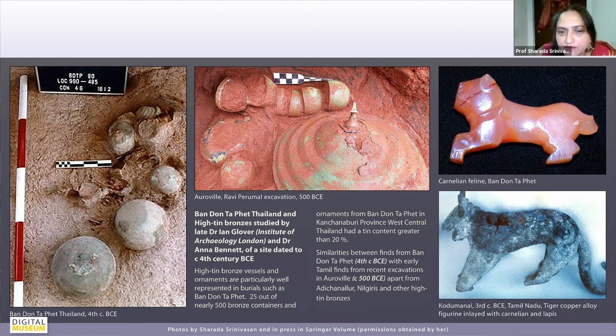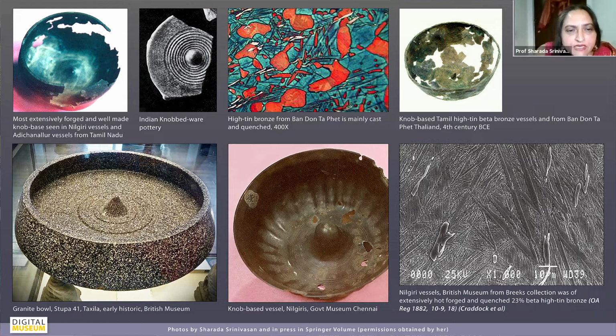And in fact, from Ravi Perumal's excavation in Auroville, you find a lot of these vessels with the finials, which are also laid down in ways that remind you of the Ban Don Ta Phet material. And now there are finds more and more of high-tin bronzes from various contexts in southern India as well. Another feature of some of these high-tin bronze vessels is the presence of this knob base, which you see particularly in some of the vessels from the Nilgiris and also in this Adichanallur vessel. And of course, in this case, the knob is part of the forging process itself. It's not added on. And it has these rings around it. And it recalls other kinds of similar depictions. For instance, there is this granite bowl from Stupa 41 in Taxila, which is in the British Museum, where you see this knob and the rings around it.